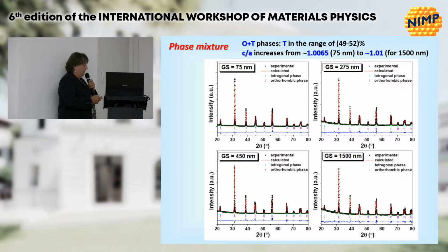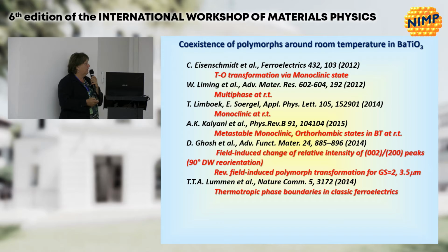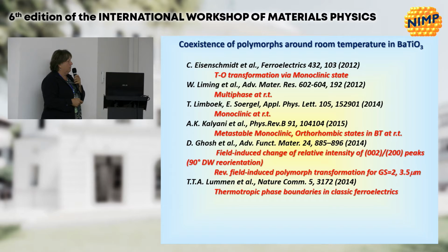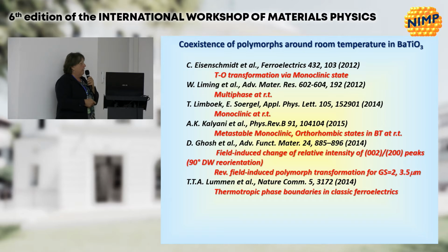At that moment, when we saw that our samples were orthorhombic, we prepared many sets of samples using similar or modified parameters, because we wanted to obtain tetragonal barium titanate, as everybody reports. However, after we found that most of them are orthorhombic, we looked more closely at the literature, and we found that in the last 10 years there are some groups that reported lower symmetry phases in the tetragonal-based state of barium titanate, either induced by some actions like field or stresses, or present in some specific conditions as a metastable state, monoclinic or orthorhombic or other states.